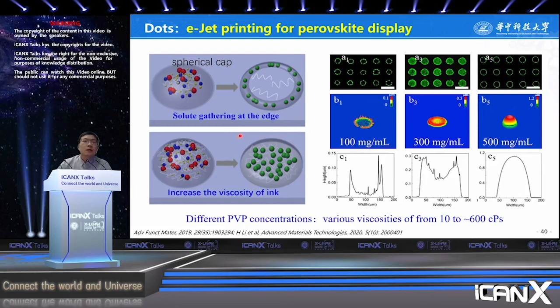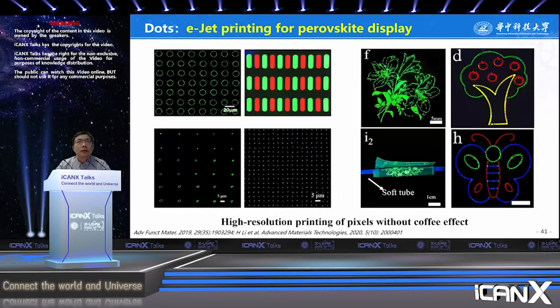Here, a perovskite solution is adopted in inkjet printing for display, and PVP is a special material in the precursor ink. Its main role is to increase the viscosity of the ink. Different PVP concentrations are adopted, giving various viscosities from 10 to 600 cP. It can be observed from the right figures that the coffee ring is effectively suppressed, like this one. It can be observed from the top left figure that dots without any coffee ring are formed.